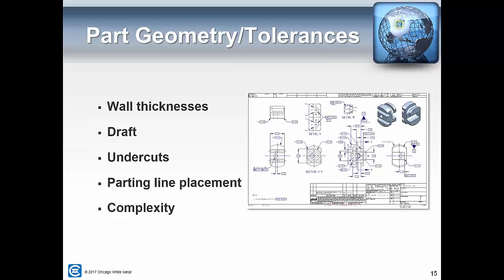Wall thickness is an important factor in die casting: you want as consistent a wall thickness as possible. When you have thicker or thinner sections than the nominal values throughout the rest of the part, that can tend to lead to defects that may or may not be acceptable. For each part that we get a PO for and eventually tool up, we go through a full simulation process where we look at the potential issues. But before we even get to that point, we use common sense to help guide you through wall thicknesses and draft, making sure that you have enough of an angle on vertical walls to release properly from the tool.